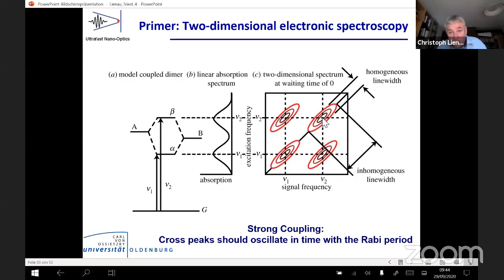It essentially contains along the diagonal of this map peaks that reflect each electronic state in the system. And then it contains off-diagonal elements, and these off-diagonal elements contain information about the coherence between the two states. So if, for example, there's an incoherent relaxation of energy between this state and that state, it would appear as one side peak that varies in intensity as a function of time. But if two states are coherently coupled, symmetric off-diagonal peaks will appear in this 2-dimensional map, and these oscillate in time. And these oscillations in time give you some information about the coupling. That was abstract. I will show an example in a second.